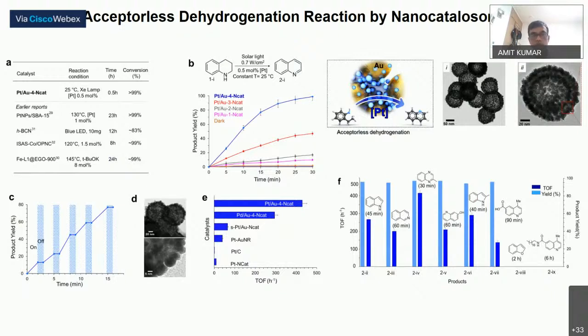And such kind of dehydrogenation reaction is very useful for generating hydrogen gas as a sustainable fuel. And we found that with 700 milliwatt per centimeter square solar light, with the help of a solar simulator, we could transform within 30 minutes. The yield of the reaction is almost 100%. As compared to the previous reports, such transformation had been tried by various catalysts. It required very high temperatures and very long reaction times. But using this kind of plasmonic interfacial chemistry, such reactions can be carried out.